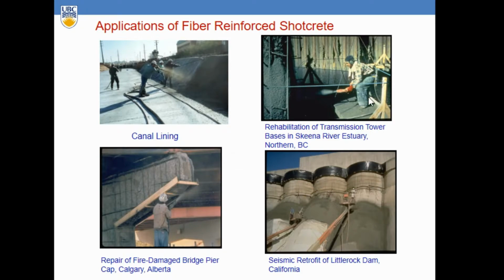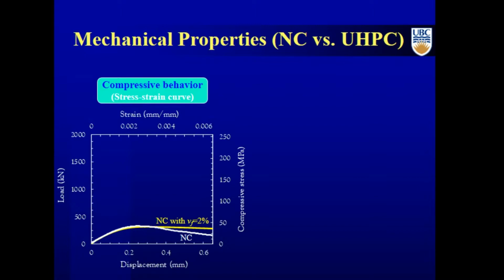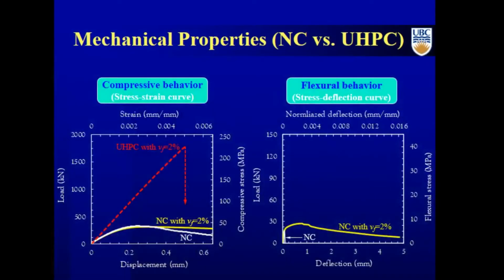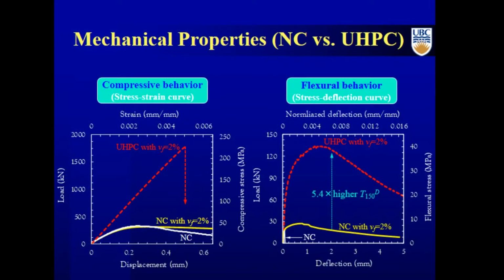Now, of late, this could be your fiber-reinforced concrete of the past. What we're doing now is trying to increase the performance of this material by increasing the strength. So you have this kind of ultra-high performance concrete, where we're increasing the strength almost up to 250 megapascal. Your normal concrete would have a strength of, say, 40 MPa. We're looking at these high-performance systems with extremely high strength and extremely high ductility. Here is the normal fiber-reinforced concrete that I showed you, and here is the material we call ultra-high performance concrete, with up to, say, 2% fiber. You can see that compared to this, we have a much, much better response, which has a number of applications: good for repair, seismic applications, blast and impact, girders, and bridge decks.